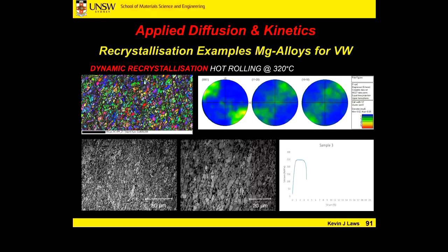So what we've got here are some of our microstructures from the rolling process. We can see here directionality in this direction. These materials were hot rolled at 320 degrees centigrade, a reduction of 50% from 3 millimeters down to 1.5 millimeters, so that was fixed. When rolling at 320 degrees Celsius, we did an analysis using EBSD on the texture of the material. Now, texture in these types of plots is represented by colour.